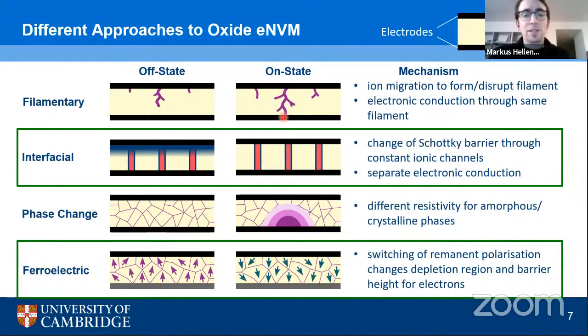The main challenge with this type of memory is that since the oxygen vacancies have to form a very well-ordered chain and thus move significantly more and with less control than in the interfacial devices, there is a reliability problem with these, because each time the filament is formed or ruptured again, it might look a little bit different than before, because the movement of the oxygen vacancies is pretty much random. So this is the difficulty with filamentary devices. The idea with interfacial devices is then that we define the channels along which oxygen vacancies can travel from the beginning. So they will not vary from switching cycle to switching cycle, but always follow the same path. And hopefully by this we can improve the reliability of this.